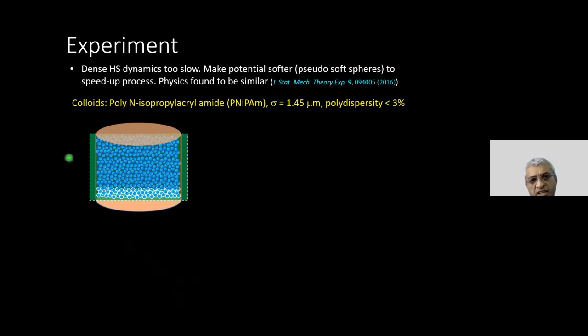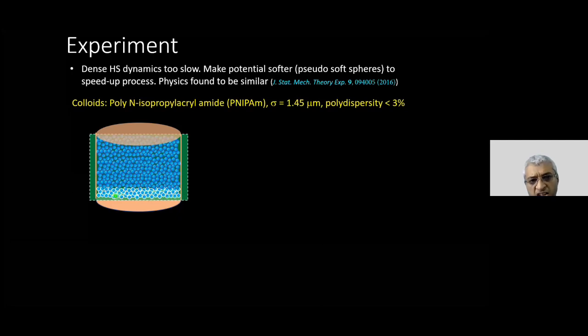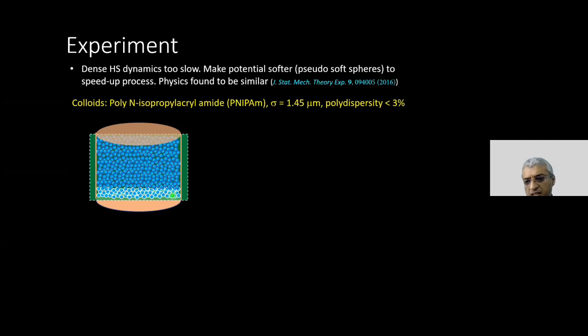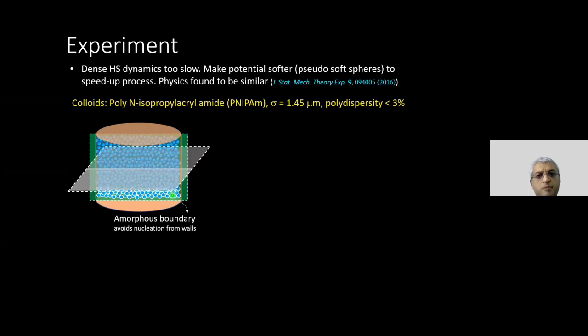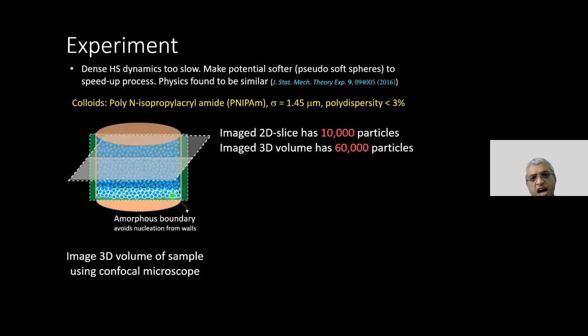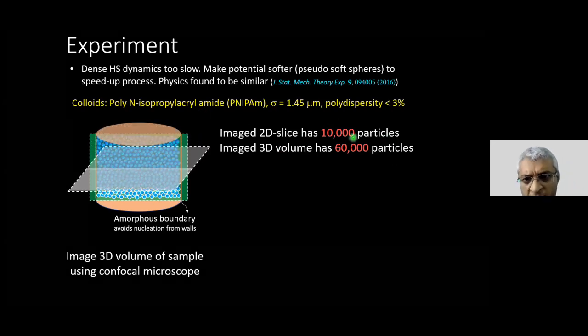So now I'm going to take these particles and put them in a chamber. Now, to prevent crystallization from the walls of the chamber, I'm going to make them amorphous by coating a few layers of particles. And then I'm going to take my confocal microscope and scan it up and down. Okay, so I'm going to track every particle in my field of view. And in our experiments, we typically have about 10,000 particles in a 2D slice. That is just the region that we focus and image. And we have about 60,000 particles in the 3D volume that we scan.